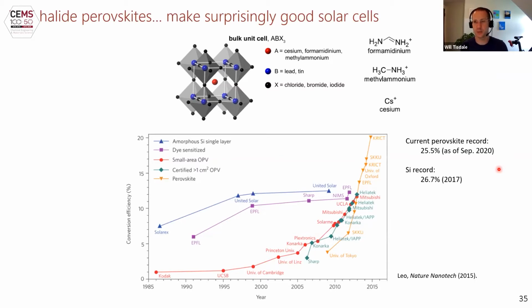Okay, but this is completely surprising because these crystalline silicon solar cells are very expensive to make. It takes high temperatures, a ton of energy, and a ton of time to crystallize silicon that is nearly defect-free, because defects in these materials are the result of power conversion efficiency losses. In contrast, these perovskites, they're actually spun out from solution or even vapor deposited. They're baked at 100 degrees Celsius or so, and then you can make a solar cell that is as efficient as silicon. So these materials must be full of defects.